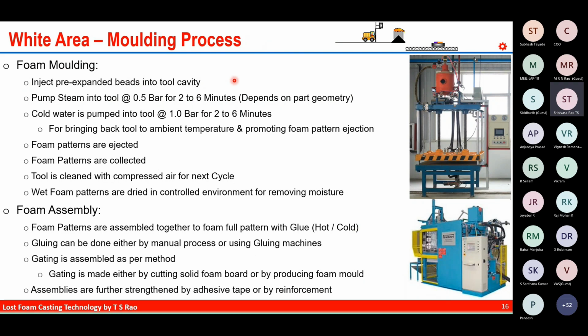The pre-expanded foam beads are injected into the tool cavity. Once the foam beads are injected fully into the tool cavity, next we need to pump steam into the tool at half bar pressure for 2 to 6 minutes, depending on the part geometry. Once the steaming is over, next we need to inject cold water at 1 bar pressure for 2 to 6 minutes, again depending on the part geometry.